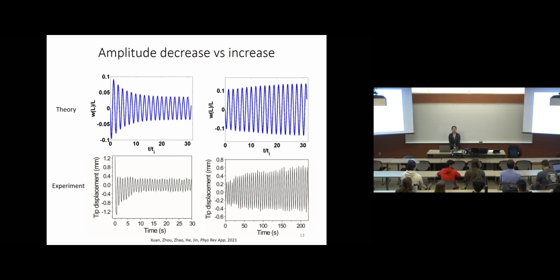And so that was going to be my follow-up question. How can you tune the frequency? Is it the mechanical properties of the hydrogel? Yeah, so if you want to achieve diffusion in hydrogel, then you have to create large pores. Large pores can speed up diffusion. On the other hand, this will sacrifice the mechanical property. But people also have some other way, so that if you locally achieve some freeze drying, you have crystallinity or some glassy components, then you can locally strengthen the material so that you can still balance the time scale versus the mechanical property. Thank you.